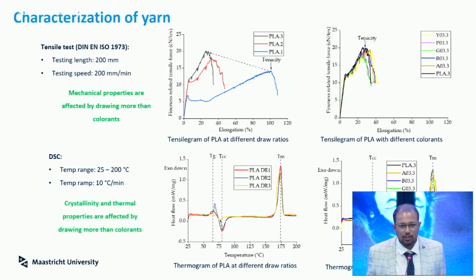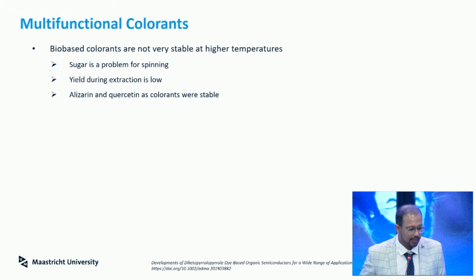This was one of the major shortcomings of the conventional dyeing process, because in bath dyeing, since you use a water bath to dye the materials, there is always a chance that you are degrading the material, which could lead to loss of strength and so on, which was not happening here.